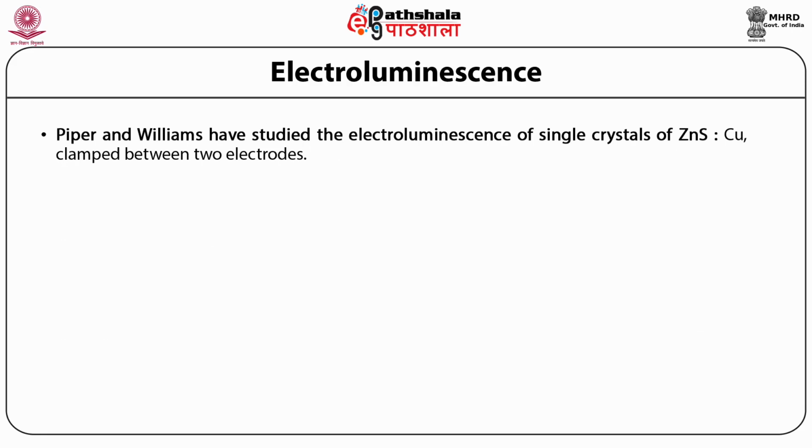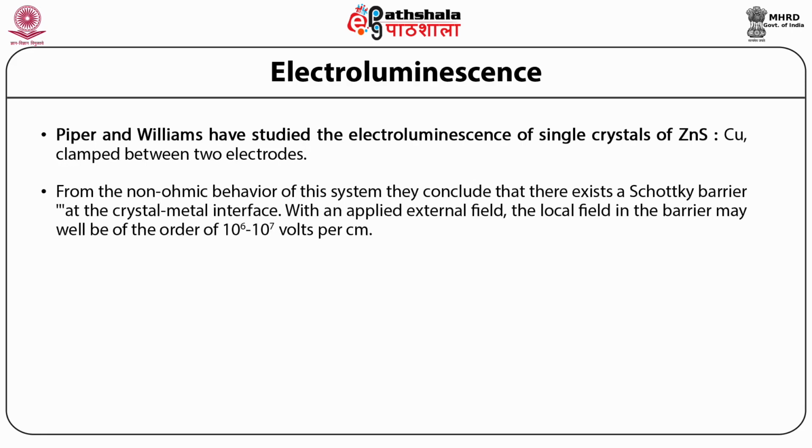Piper and Williams have studied the electroluminescence of single crystal zinc sulfide copper clamped between two electrodes. From the non-ohmic behavior of this system, they conclude that there exists a Schottky barrier at the crystal metal interface with an applied external electric field. The local field in the barrier may well be of the order of 10^6 to 10^7 volts per centimeter.